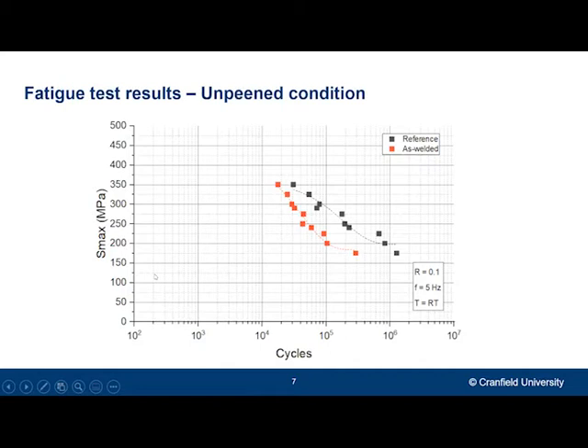So here you can see the difference between the pristine aluminium material with no weld, which is the reference in black, and samples that were friction stir welded without any defects, presumably, and which I'm calling as welded and are in red. And please be reminded that this is before any peening treatment yet. So we can conclude that by using friction stir welding, we're reducing the life for about 70% when we compare it to just the pristine aluminium material. And this is obviously due to the challenges that I talked about earlier, mainly the softening effect happening at the joints, as well as the residual stresses that are involved in the process.